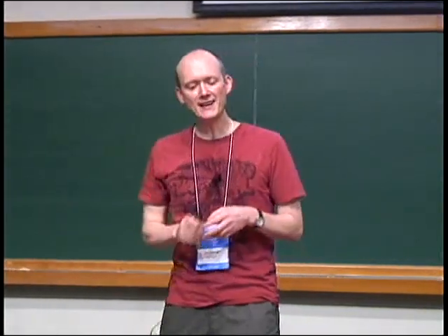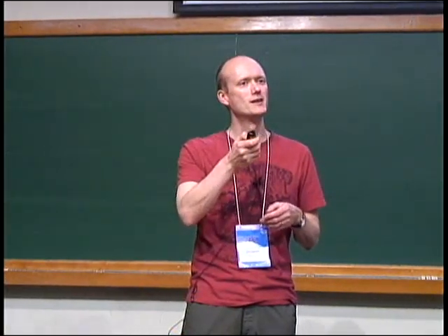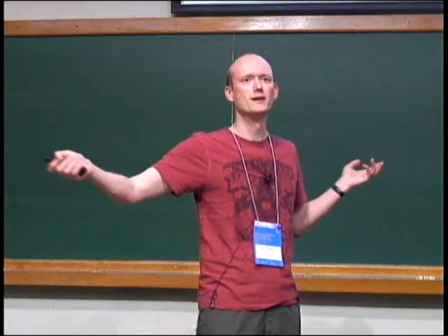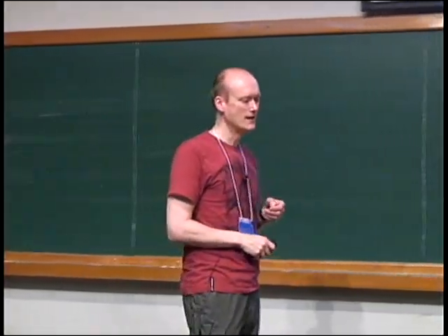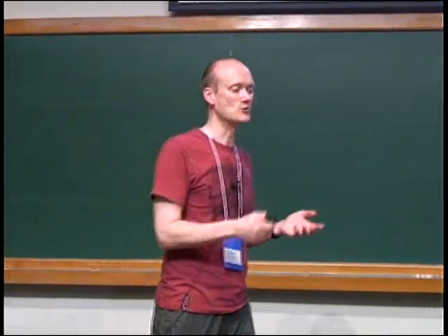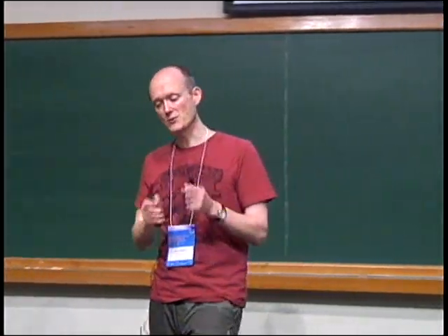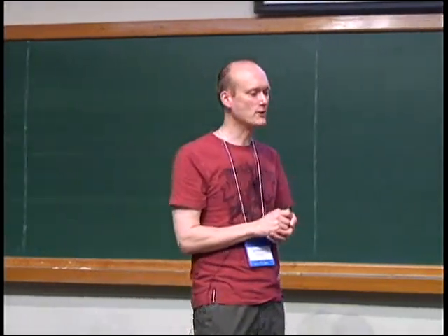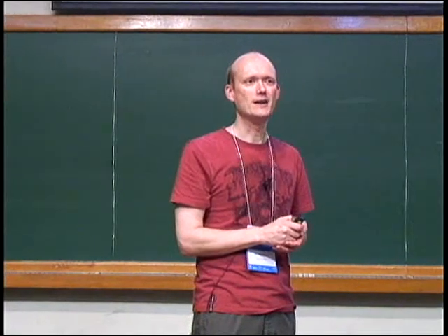But if I give any little perturbation to the vortex, then I change what the tangent is. And then suddenly J cross T is not 0 anymore, and it's going to move. And that's what's causing this instability. It wouldn't happen for a fluid because you didn't do this cross product. But the cross product means that you can give an infinitesimal perturbation to the vortex, which can change the normal by a lot. And that's what's happening.